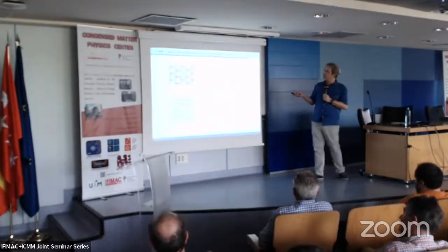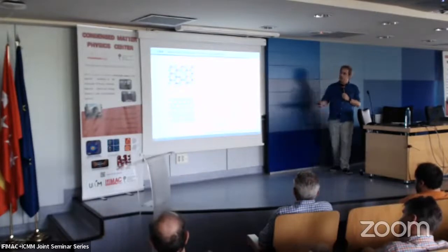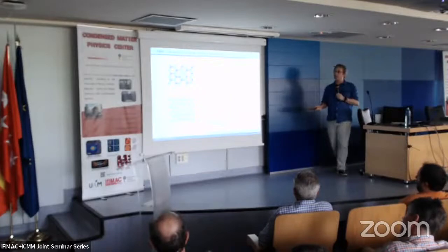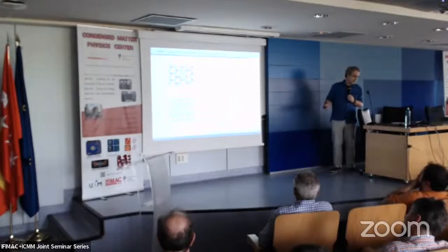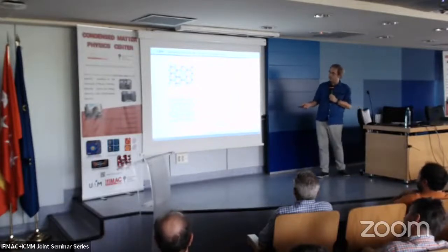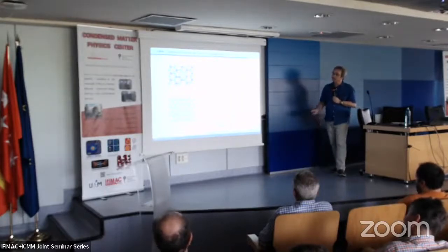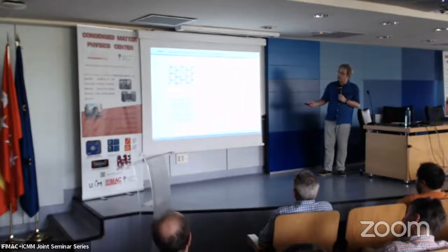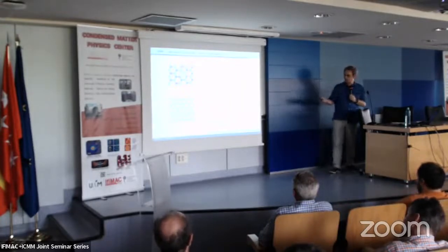And to finish off, the calculations which were made by Pablo Garcia were calculating one defect with the nitrogen in the boron site and the vacancy of the nitrogen, and the three borons and one nitrogen missing, and one boron missing. With the density functional calculations, we can show that there can be levels inside the visible range giving rise to this emission, as two examples here.